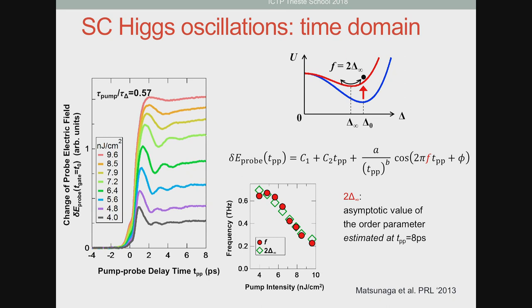Right immediately after the pump, there is an increase of the transmission. This increase of the transmission can be interpreted as a reduction of the gap, so you are killing your superconducting gap a little bit. And then you can see oscillations.